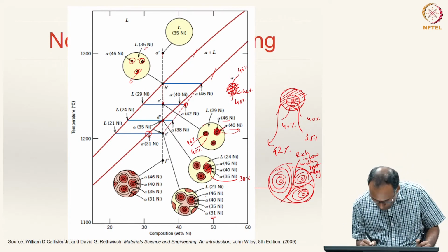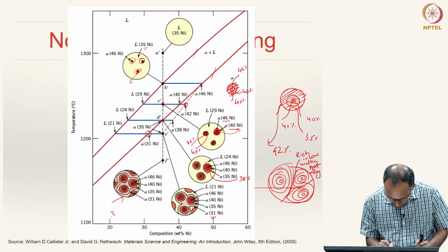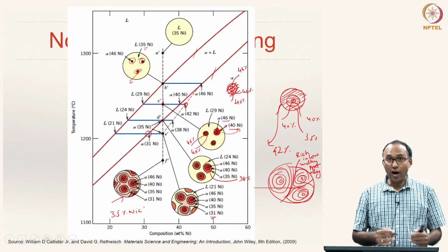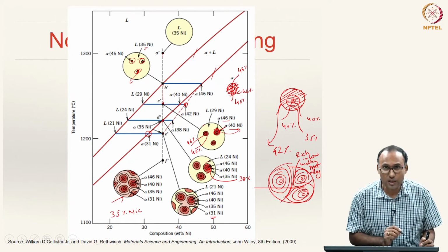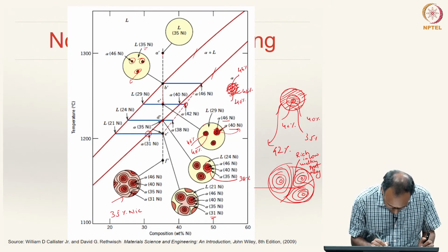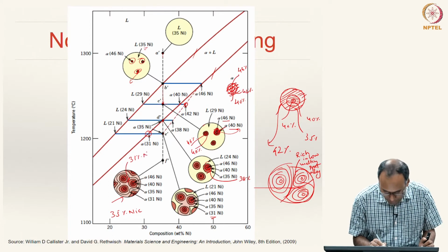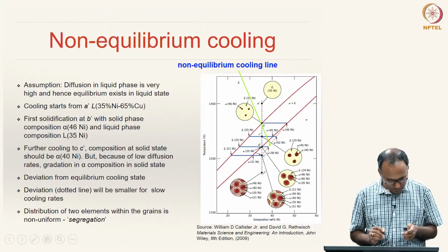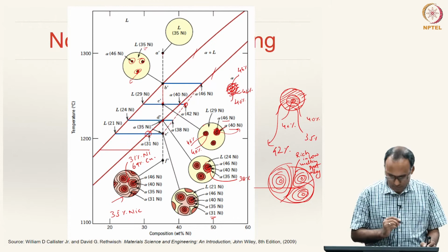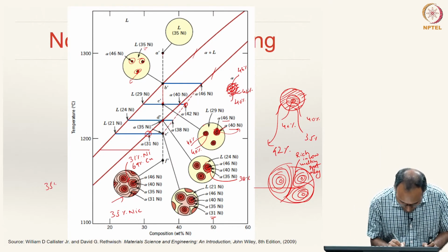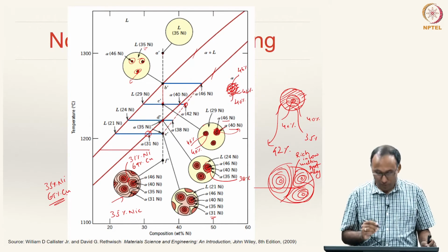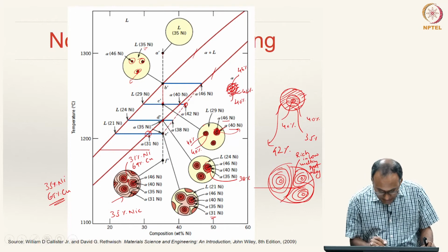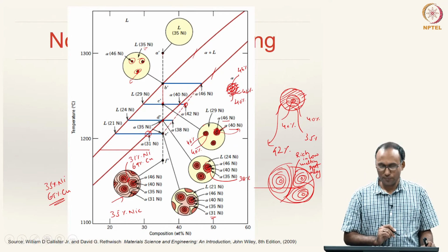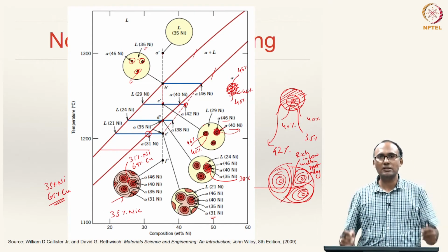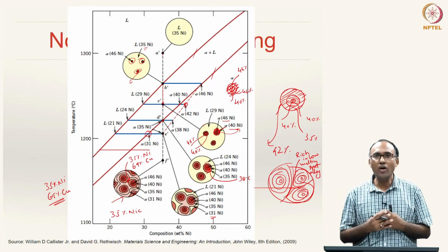So, here you see normally this should have been 35% nickel. On an average it will still be 35% nickel, but in here you also have regions of alpha which are particularly this one has 31% nickel. 31% nickel means 69% copper, as opposed to 35% nickel, 65% copper. That means, you have the low melting alloy getting segregated near the core, near the boundary between two particles. So, such a cored structure is an outcome of non-equilibrium cooling.